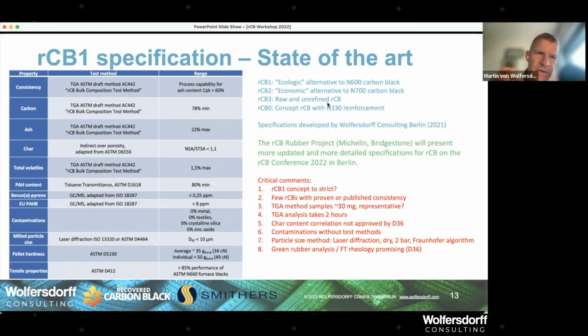So the idea for this specification, in my client work, both with the tire industry and with the recovered carbon black industry, was to give them guidance of what the best recovered carbon black could look like, and then maybe have a second quality, the first one being ecologic and the second one economic. The raw and unrefined recovered carbon black, RCB3, has very little commercial value. We'll look at prices in the second session. And then I created the concept recovered carbon black RCB0, which is the holy grail, which has the reinforcement of an entry-level hard black, the ASTM 330.